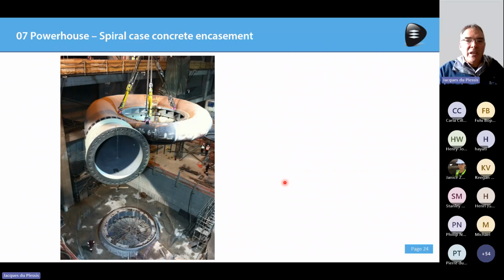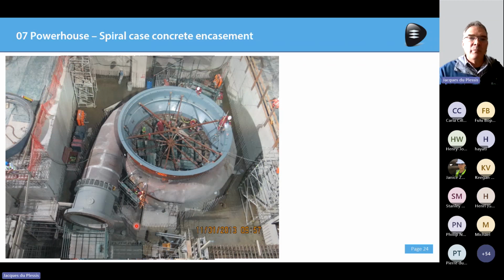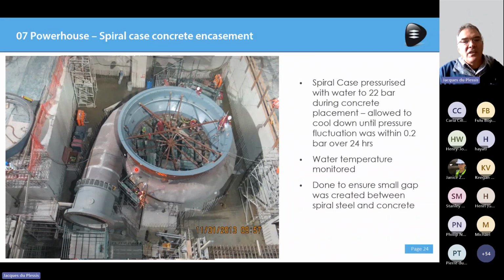Now, we don't have too many more slides to go. So the spiral case around the turbines were put in position. Remember, there were 4 of these, and a very interesting part of the design. What we wanted is between the spiral case steel and the concrete, you want a small gap. Because what you want is when this is pressurized, you want the steel of the spiral case to first take up the first initial load, and then only does it get supported by the concrete around it, by the reinforced concrete around it.